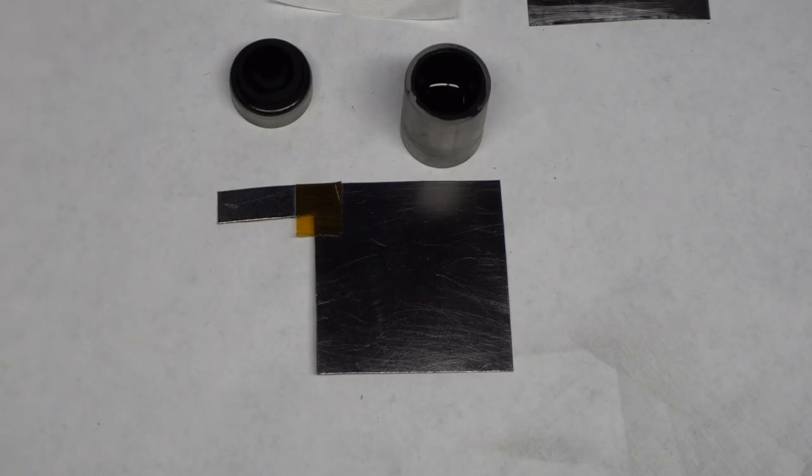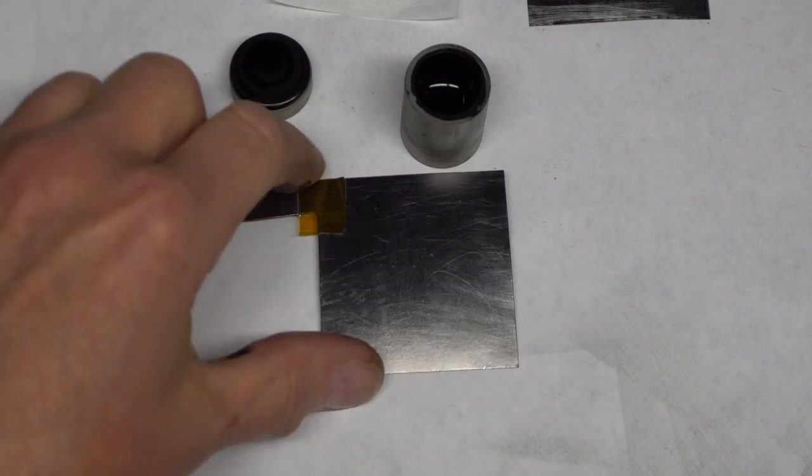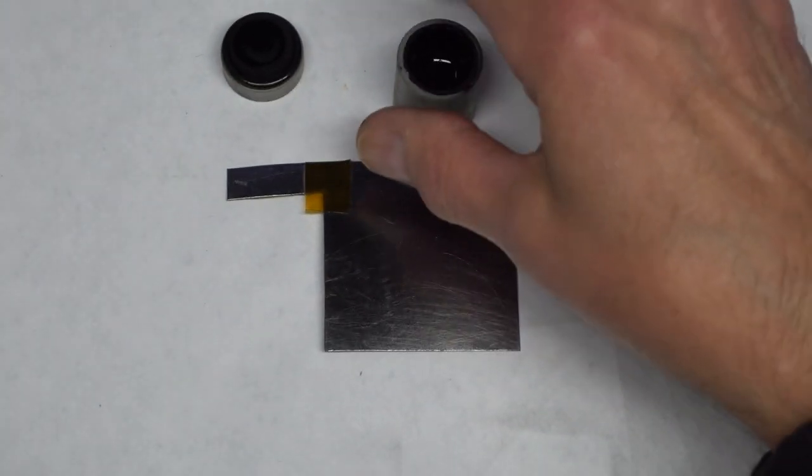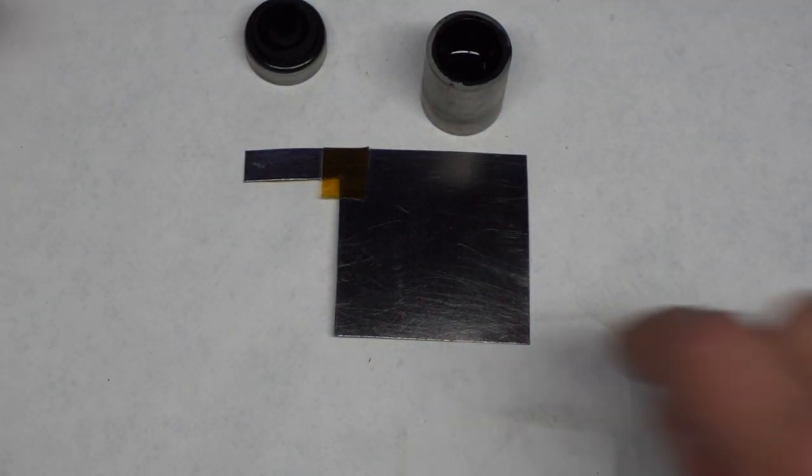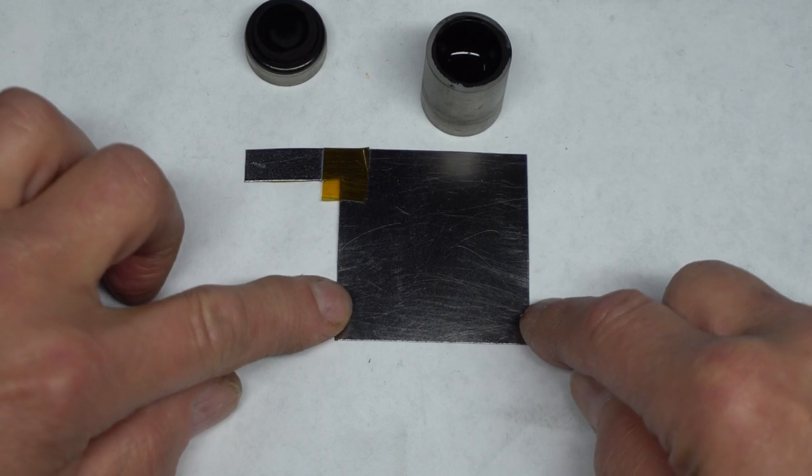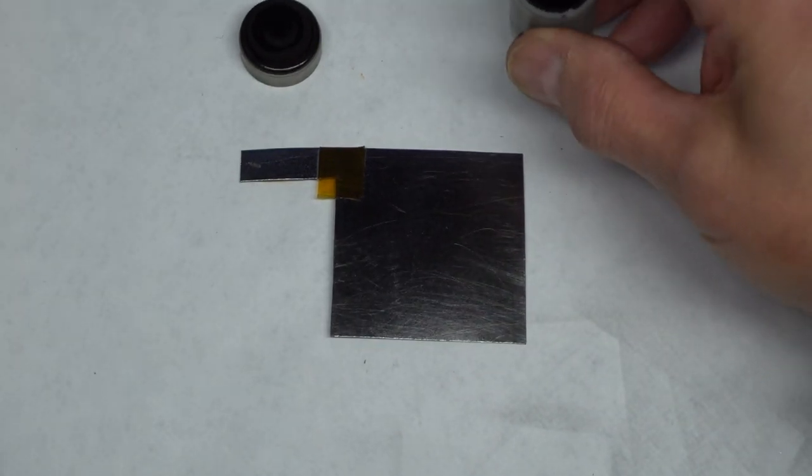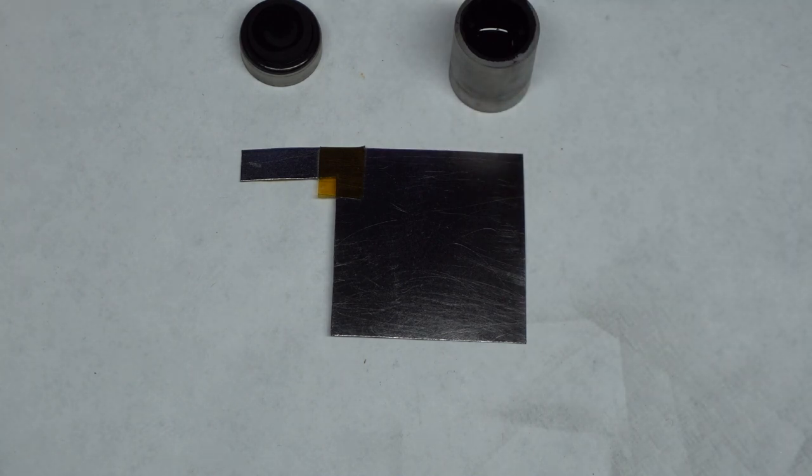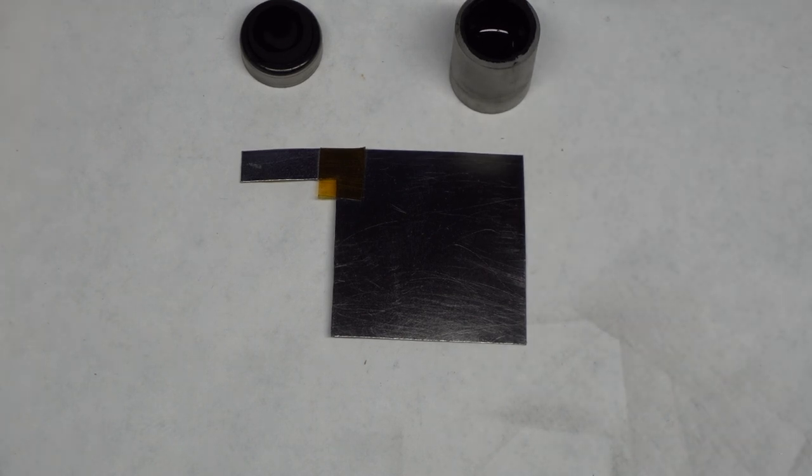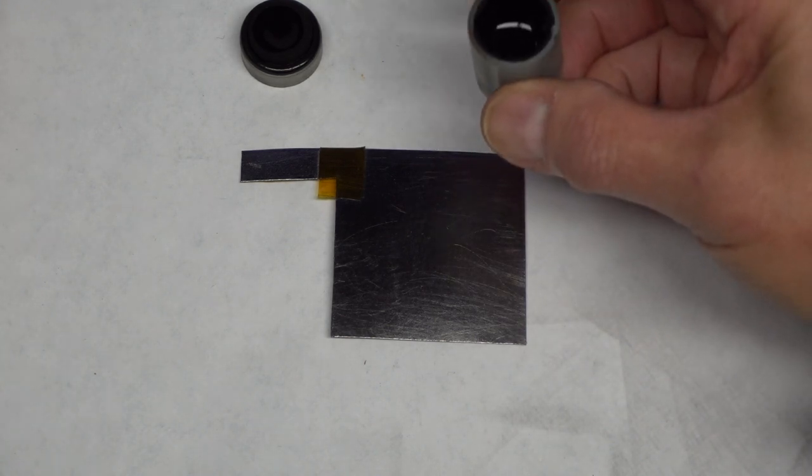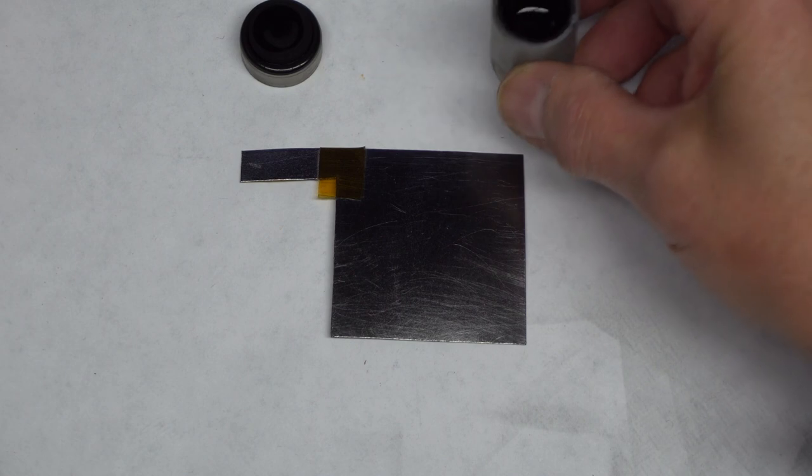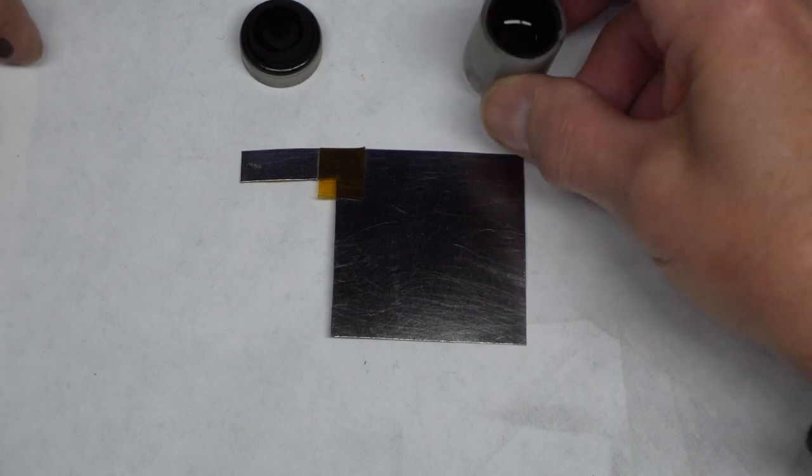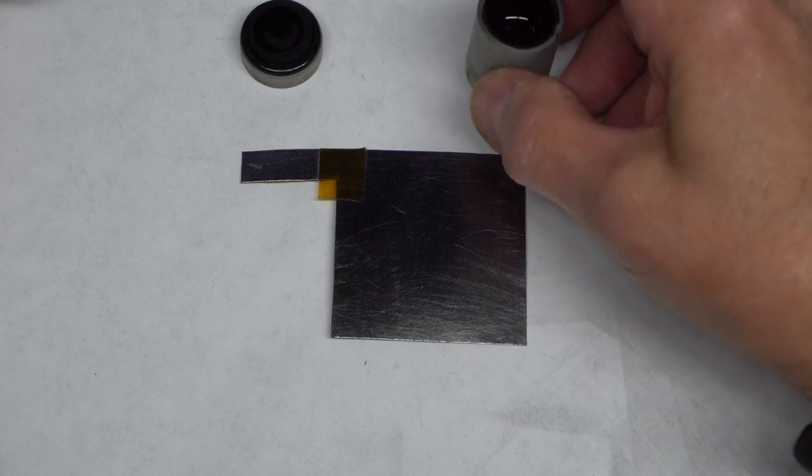Okay, the next step is to coat the laminated graphite foil collector with active carbon material. The area of this collector is two by two square inches. I'm not going to show you how to make the active carbon ink in this video because formulations are already covered in great detail on other YouTube channels, such as Robert Murray Smith and KREX2. The links to these channels are in the description below. But I will say that it is mainly made up of sulfur doped sugar charcoal with a CMC SBR binder and water as the vehicle.